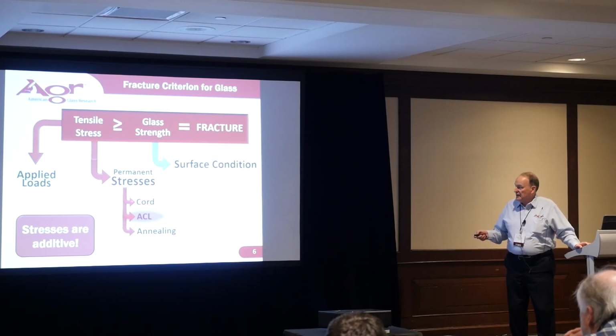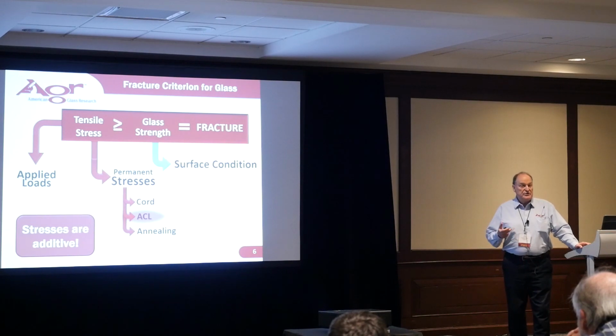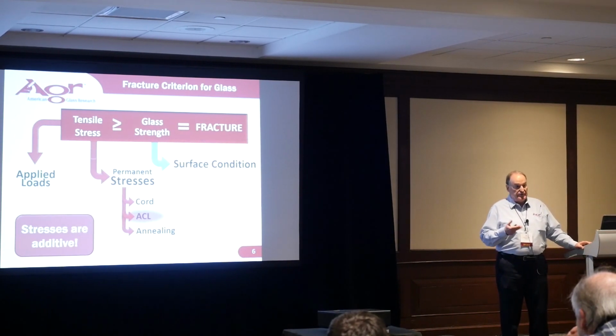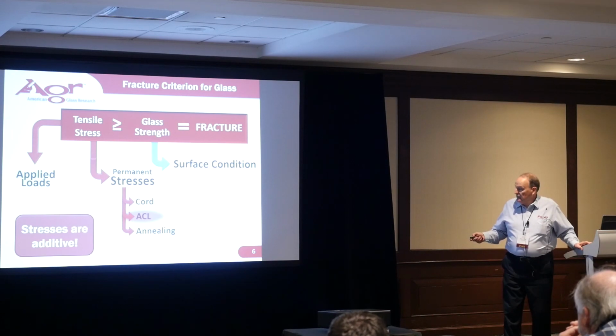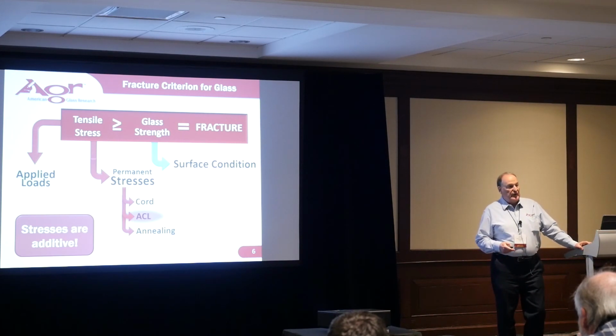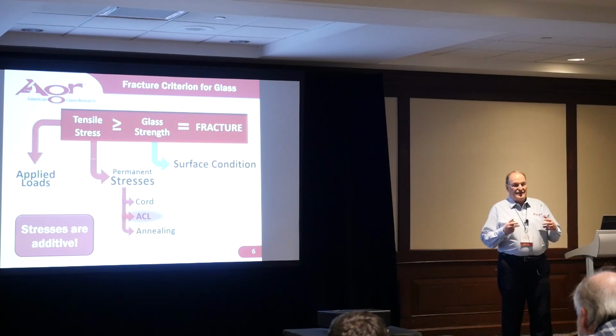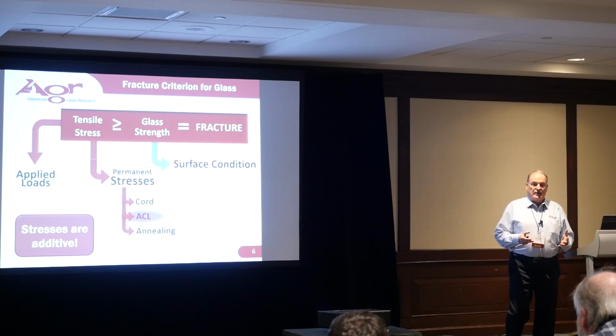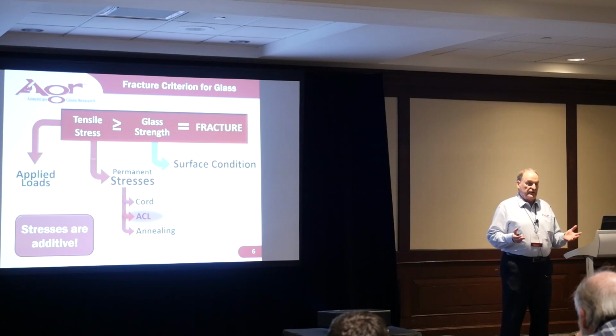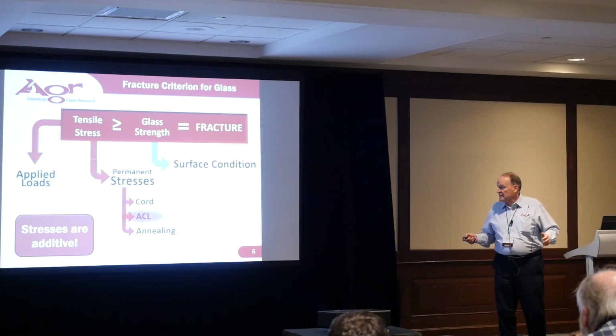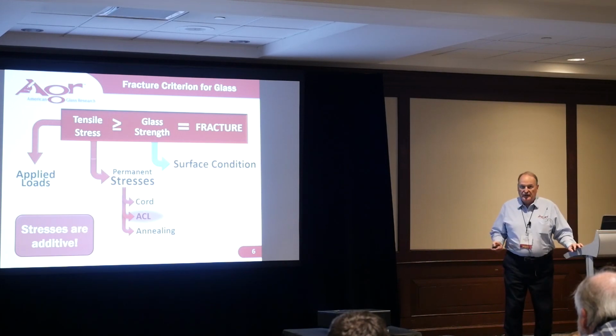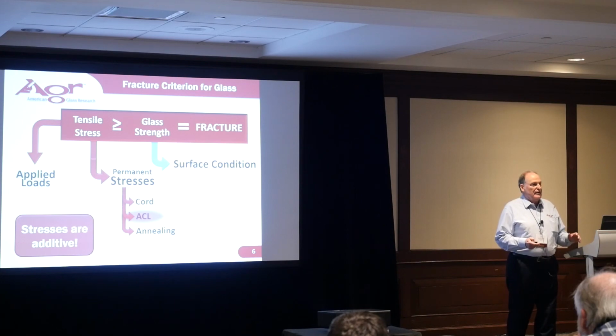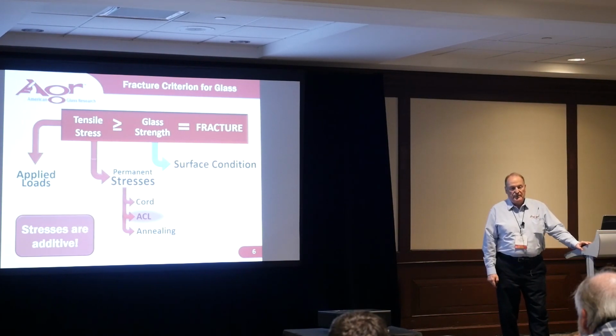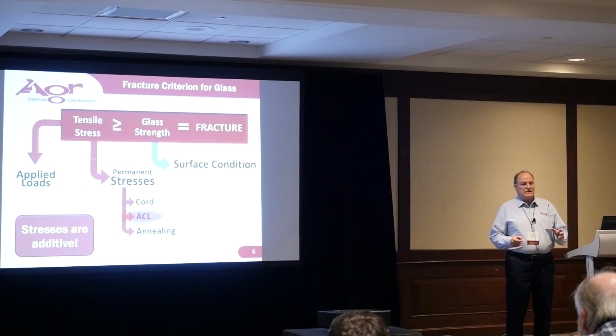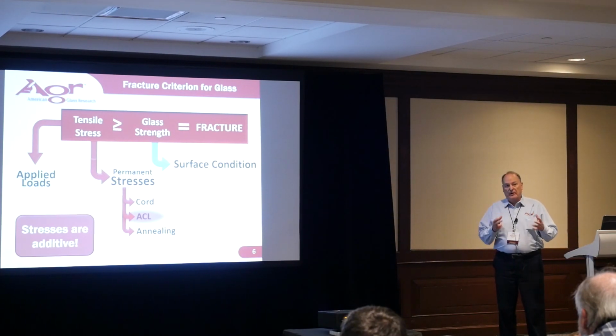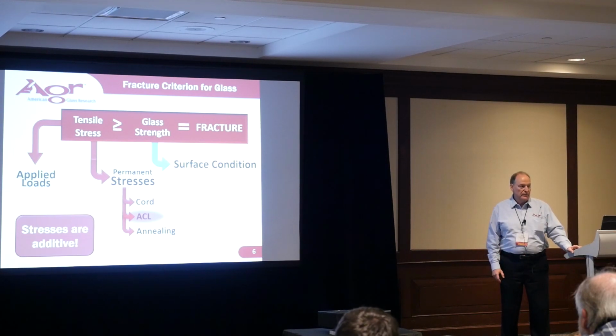On this list are things like cord, which is an inhomogeneity in the glass itself that's coming out of the melting furnace. It could be annealing, which I mentioned earlier. If bottles are poorly annealed, there will be tensile stresses in the structure of the glass that exist for its lifetime until that container is broken. Also on this list is why you're here for the last day and the rest of today. These applied ceramic labels. All of these can be creating stresses that become inherent in the structure, are permanent, they exist until the bottle is broken.